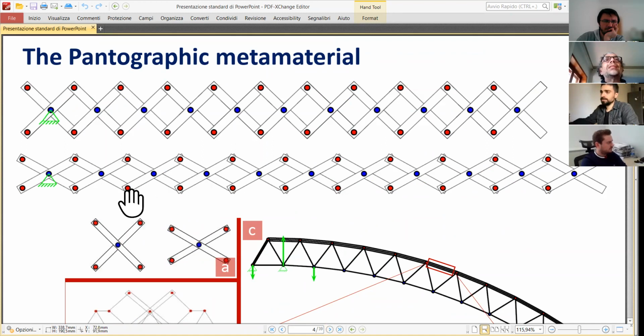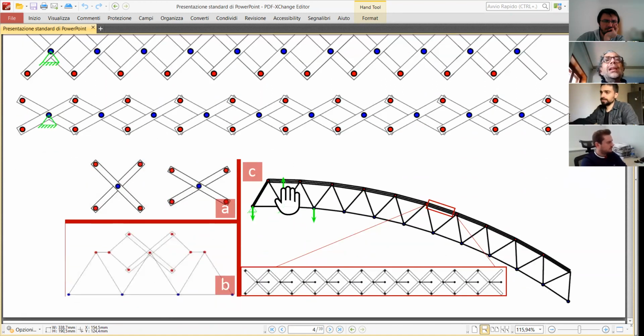Look, this is the Pantographic structure made of flexible beams, and I used this microstructure for getting another interesting object, which is what is described in this C. This is the microstructure. If we zoom in on this upper beam, we find this microstructure, and this is a very unusual beam. This beam can change its curvature, if it is uniform, without energy. So the deformation energy of this beam depends on the third derivative of displacement, which is a rather exotic metamaterial.